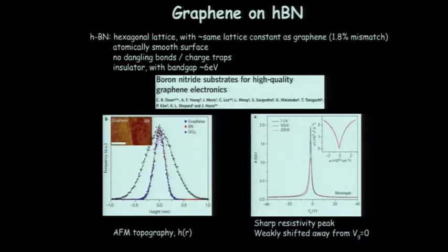But more importantly, there are many charge traps in there. There's dangling bonds on the surface of the oxide. And so that's not really what you want if you're going to put your graphene right on top of that. And the third requirement is that it's an insulating substrate. So silicon oxide fulfills basically one of these three requirements. Boron nitride can actually fulfill all three of them. And so the idea was that this boron nitride would just act as an inert substrate. We could put our graphene on it, and we'd be all set with that.